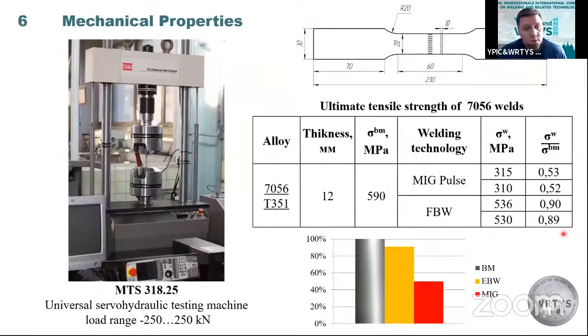Investigation of mechanical properties was provided on a universal servo-hydraulic testing machine with a load range of 250 kilonewtons. We tested specimens that you can see in this picture, and after testing, we can see that welds of 12 millimeter thickness welded with MIG technology give near 0.5 of base metal strength, and flash butt welding gives us near 90% of base metal strength.